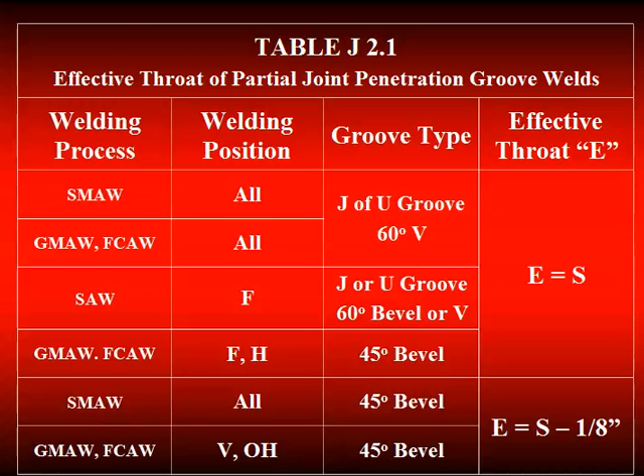But if we take that same process, shielded metal arc, regardless of welding position, and we use a 45-degree bevel, then the effective throat E that we get is equal to the depth of bevel, S, minus 1/8 of an inch. And if you go through the table, you'll find that there's actually ranges on these angles. And if you have the larger angles, E is equal to S. If you have smaller angles down to 45 degrees, you subtract 1/8 of an inch off of S. And less than 45 degrees isn't permitted because we can't reliably get fusion to the root.